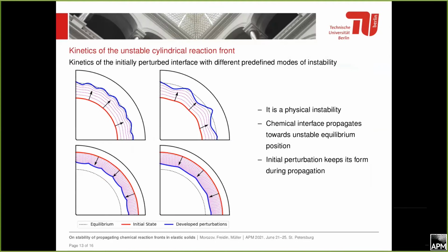And the last slide: if we introduce some initial perturbation to our interface, it remains in unstable configurations. The shape of the initial perturbation remains, however, the amplitude grows during the propagation. And that also fits our analytical prediction. So the unstable interface is unstable at every point, not only at the equilibrium.